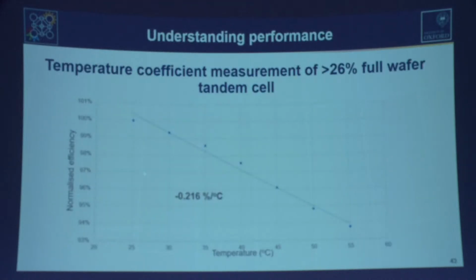For anyone who's actually in the field and interested in these sort of things, I'm showing efficiency against temperature here. This does bear relevance into how much power we will generate from the module while it's actually deployed. So when we measure the efficiency of a module, the standard temperature is 25 degrees centigrade, but actually on a sunny day, a module is never going to be at 25 degrees. It's always going to be hotter. And for thermodynamic reasons, solar cells lose efficiency as they heat up. It's part of the process. And there's something called temperature coefficient, which is how much efficiency we lose per degree. A typical high-quality silicon module today will lose between 0.3 to 0.4% per degree. And actually, these tandem cells and modules lose much less, so only 0.2% per degree. So that means we're going to generate more power at high temperature, which actually means the energy yield, which is ultimately what's important, is going to be pretty good.